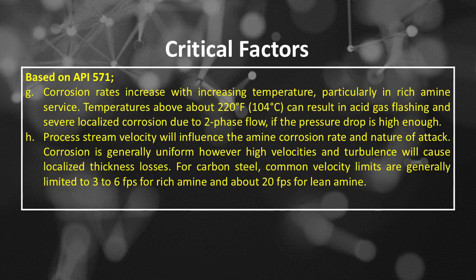And number H. Process stream velocity will influence the amine corrosion rate and nature of attack. Corrosion is generally uniform, however high velocities and turbulence will cause localized thickness losses. For carbon steel, common velocity limits are generally 3 to 6 feet per second for rich amine and about 20 feet per second for lean amine.